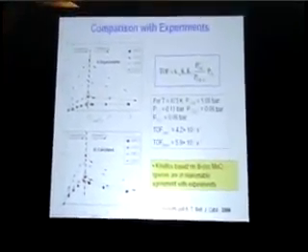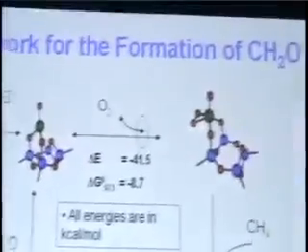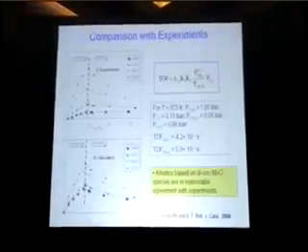So we have been able to make some interesting deductions. I'll go back here one slide. We've shown that this is the active center. Very likely the peroxyl that you form at this stage of the chemistry is the important oxidizing species, and it's the addition of methane against this peroxyl that gives you the final chemistry.